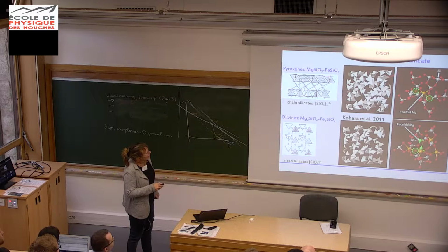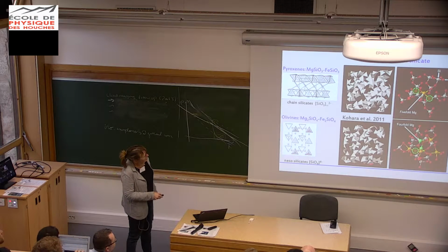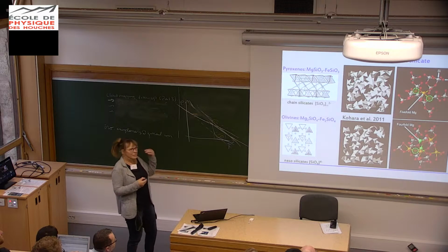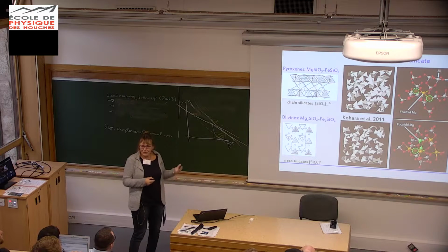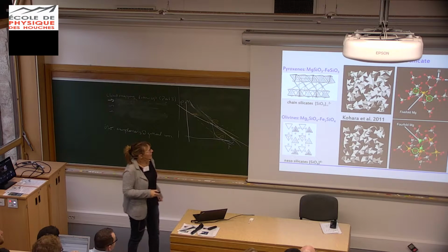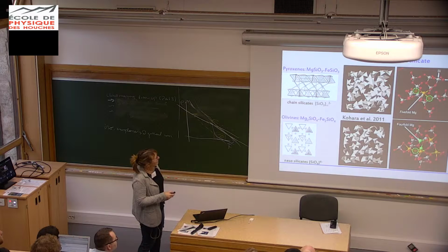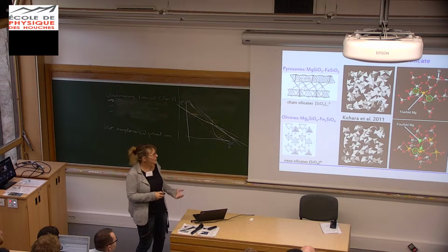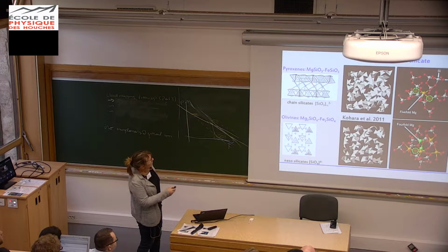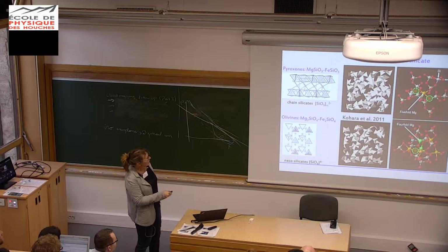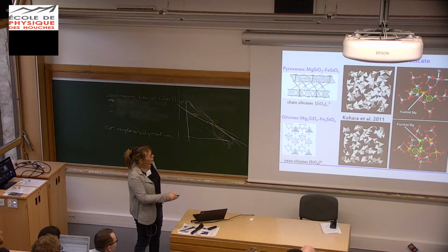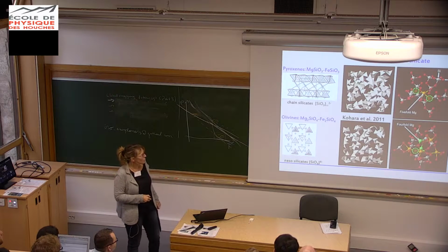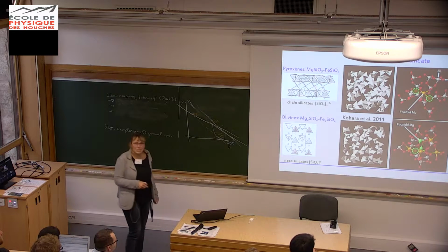You can see in this snapshot how the SiO4 tetrahedra are condensed in such an amorphous structure. You can imagine that 5 seconds later, it could be completely different. Also here you can see there are differences in the coordination spheres, for example for magnesium or iron. Normally you have a 6-fold coordination, but you also have 5-fold or 4-fold coordination in the amorphous material, with additional oxygen somewhere.